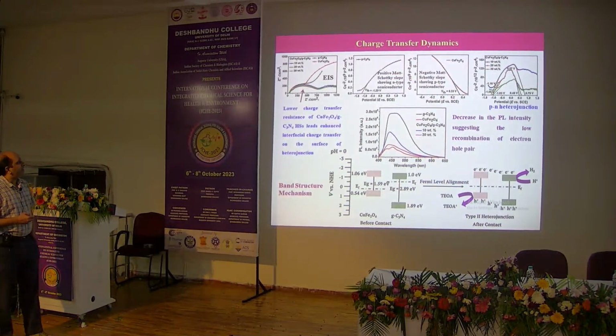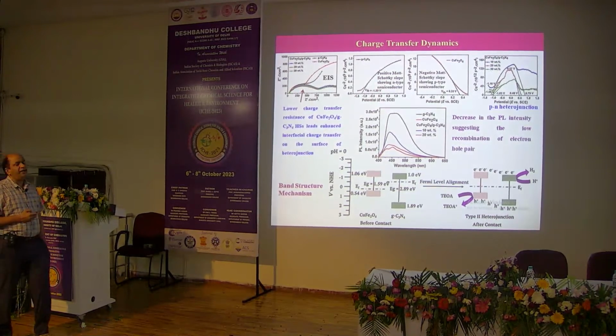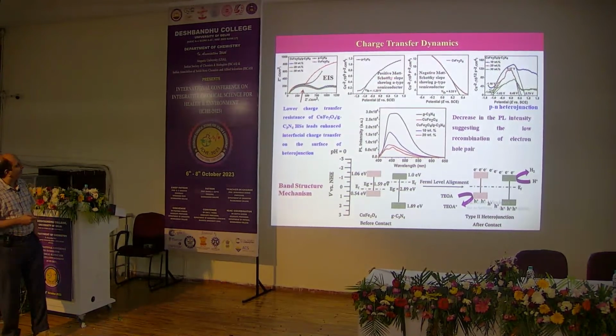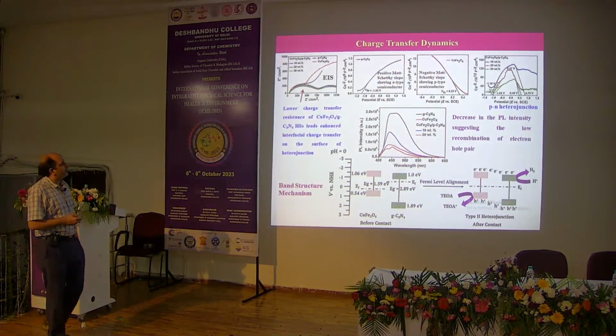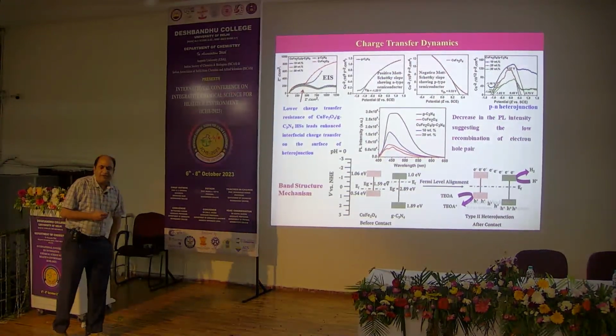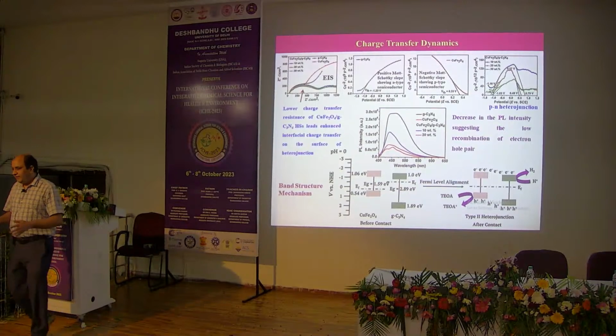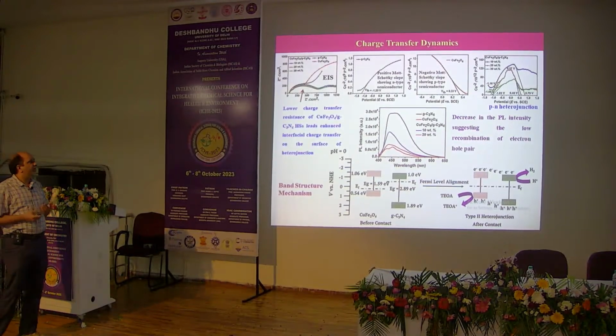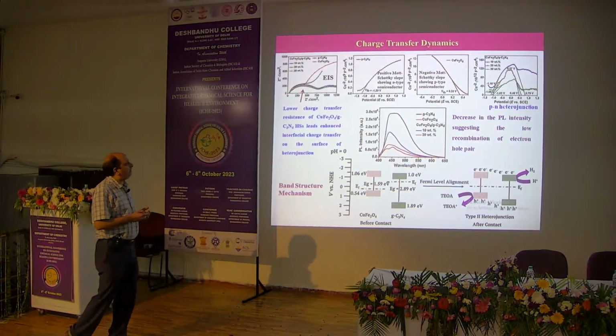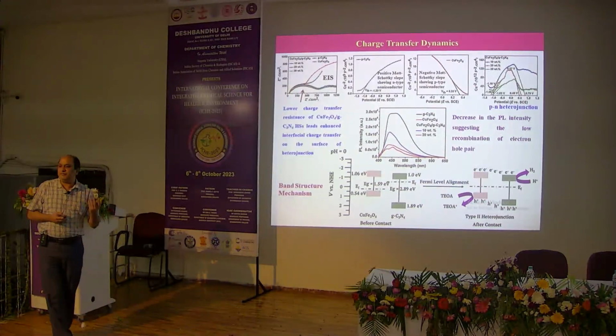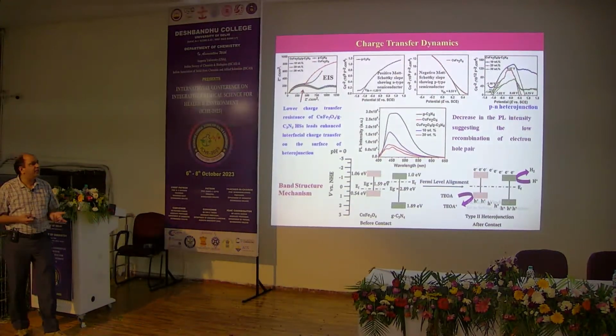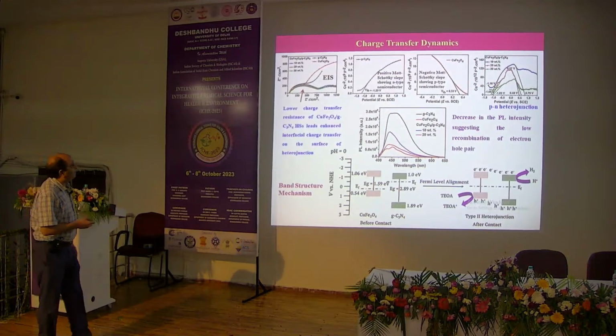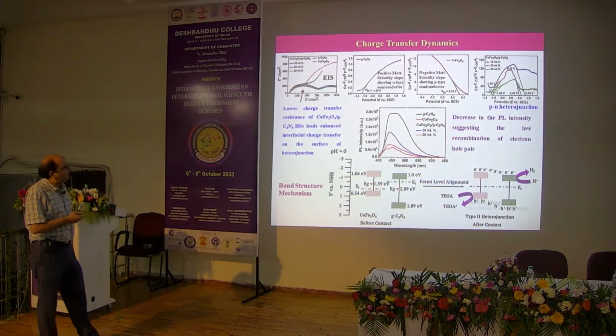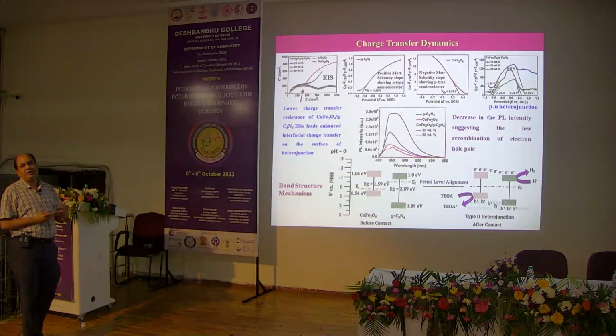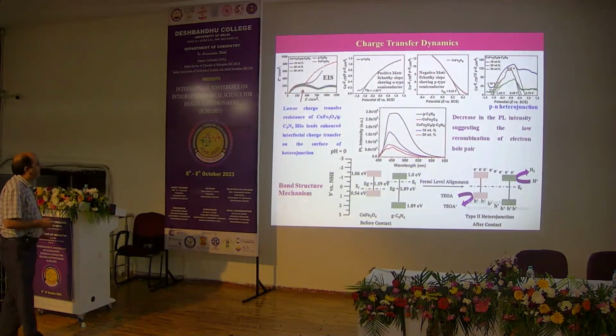This is for the graphitic carbon nitride, and here it gives the positive Mott-Schottky plot, which refers to the N-type semiconductivity in graphitic carbon nitride, and the negative Mott-Schottky plot in copper ferrite refers to the P-type semiconductivity. And when you have the heterojunctions, then you can see both the positive and the negative Mott-Schottky plots, which refers to the PN junction formation of these heterostructures. And this is the PL plot, and here you could see the decrease in the PL intensity, which suggests a low recombination rate. And this is the band structure mechanism.